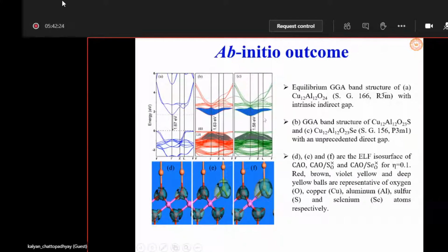In the selenium-doped system, the result is more or less similar. It also becomes a direct band gap, a light hole state is generated, and there is a significant improvement of the density of states. When you look at the electron localization function (ELF) plot, you get the same thing. You see, when oxygen is replaced by sulfur, this is the region which is oxygen deficient, electron deficient. So that means hole dispersion has been achieved.